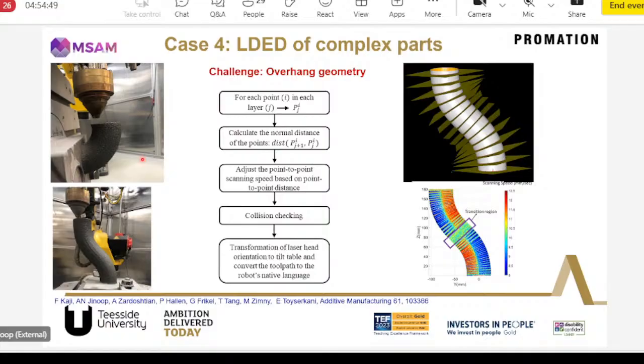So we tried to make this sort of overhang geometries. If you see this sort of bended pipe structure, we can see that in a specific layer, the thickness of the layer is less at one side and higher on the other side. So in a specific layer itself, we need to have a lower height at one zone and a higher height at the other zone. So we need to play with the process parameters here. You can see that one particular zone was printed with a higher scanning speed, while the other zone was printed with a lower scanning speed. So within a layer, we can vary the height. Again, this is the beauty of the process.